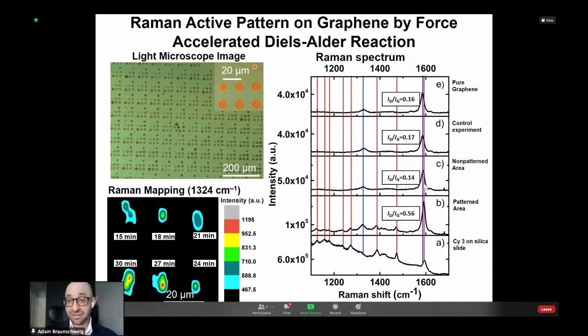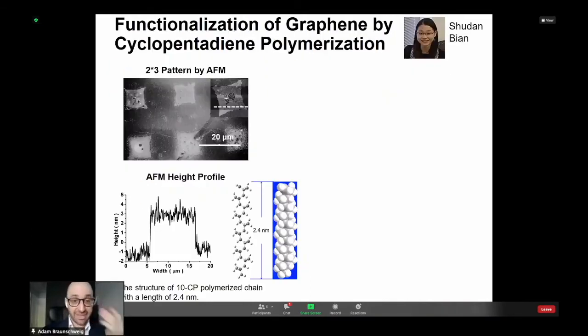In a non-patterned area, the same, but in the patterned area where we exerted force and we have our diene present, what you see is not only an increase in this ratio, but you also see the peaks corresponding to the Raman dye. And the reason why this peak increases in intensity is because this peak is characteristic of the sp3 bonds within graphene. So this was the first confirmation that this does in fact work. And then AFM also showed us it worked. However, the monolayer should only be a few angstroms tall, but our features were several nanometers tall, and this didn't make a lot of sense to us.